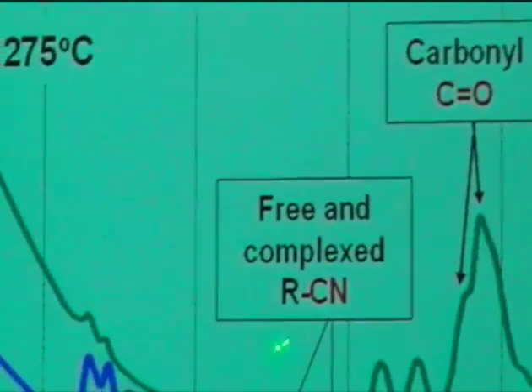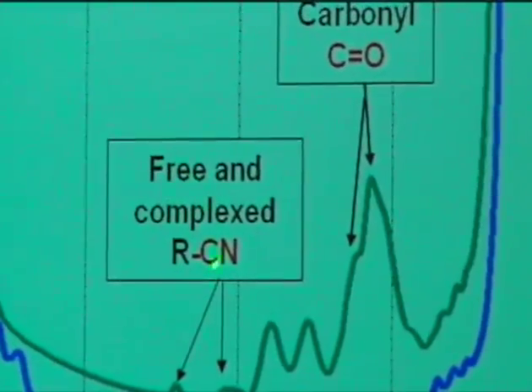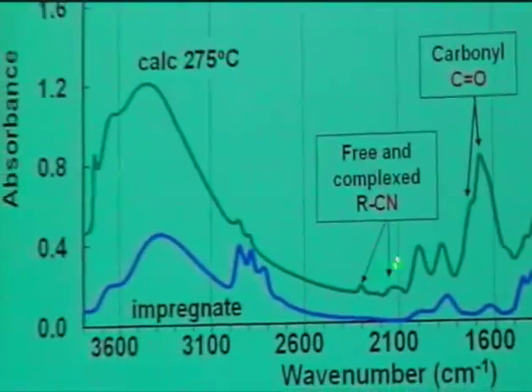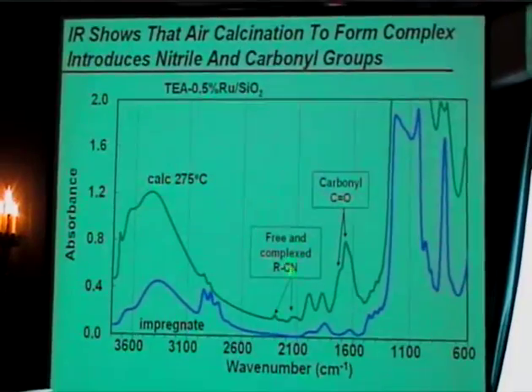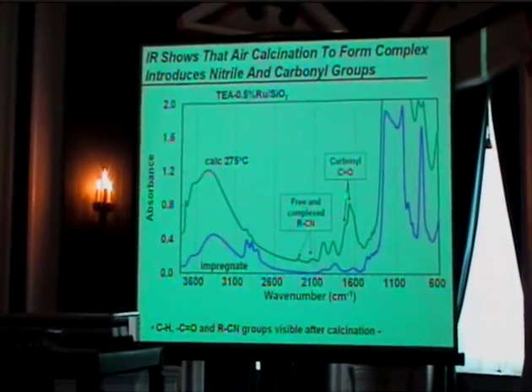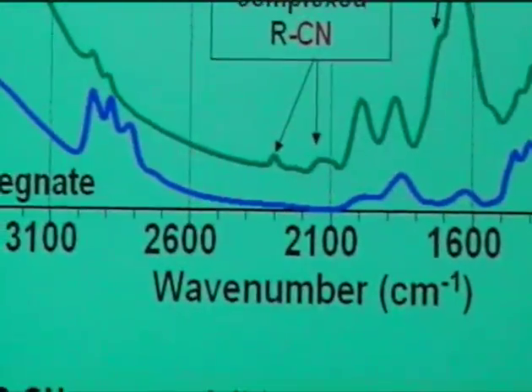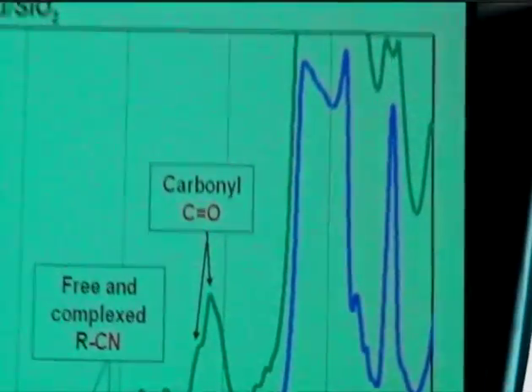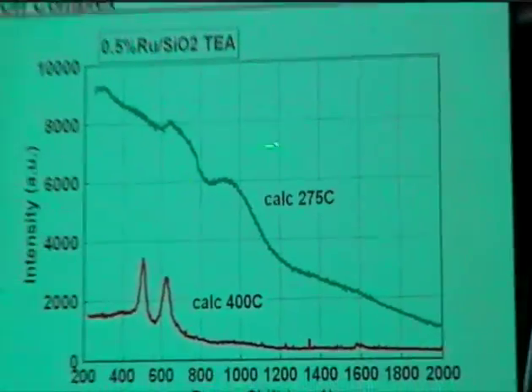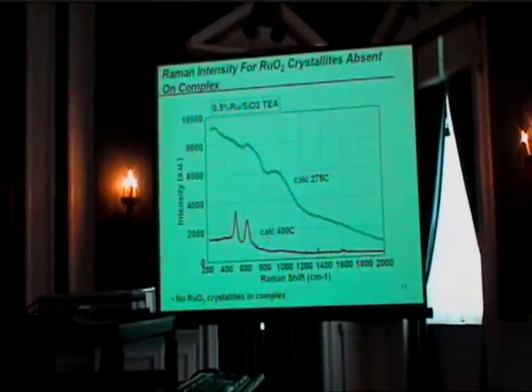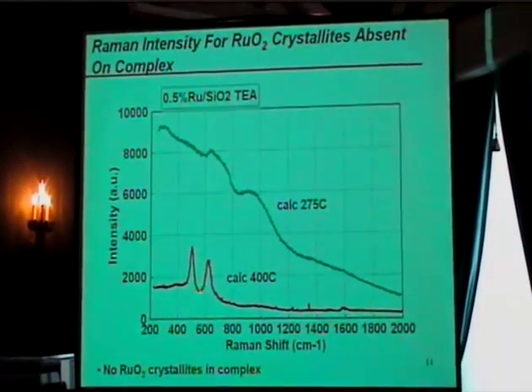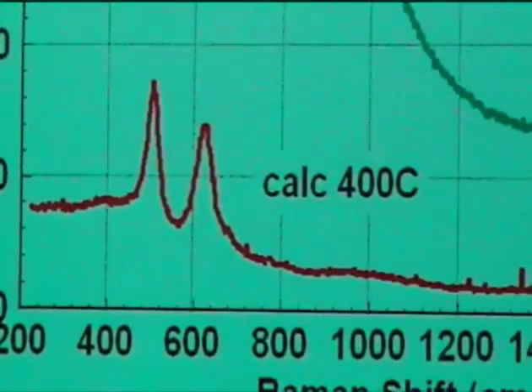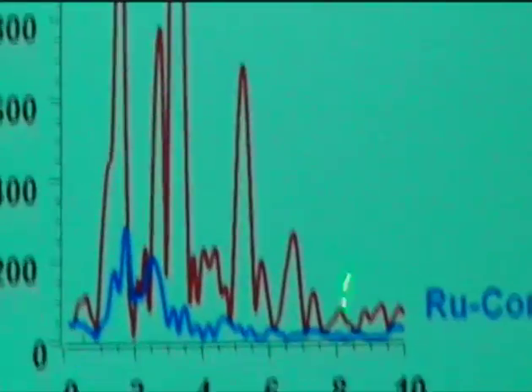Infrared is shown, actually, we think that this is part of the critical component, that we have actually made a nitrile type species that's complexed to the ruthenium, and we see peaks for that as well as some peaks for the CO. And that occurs after the impregnate is calcined. So we think that that is an indication that that nitrile species is what's actually coordinating with the ruthenium. We looked at the Raman, and you can see the nice peaks that you get for the calcined version where you have large RuO2. Those are just not there on the complex. Same thing on the XAS results.